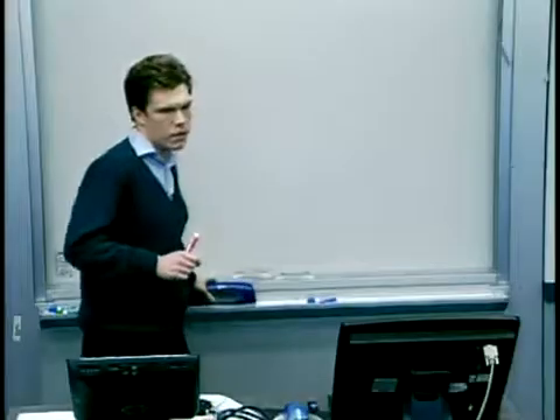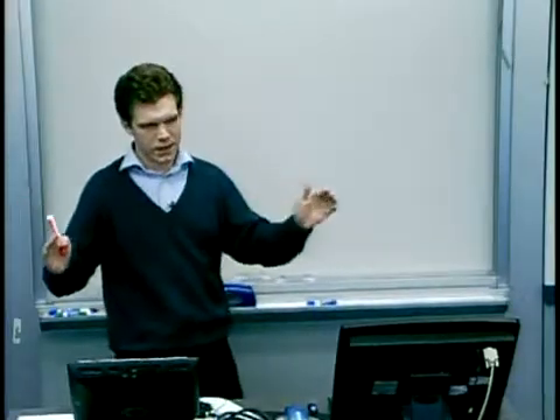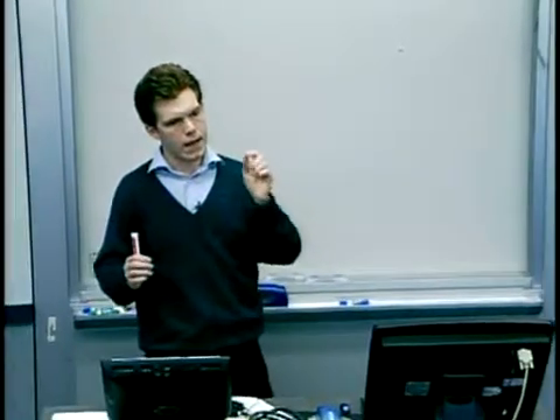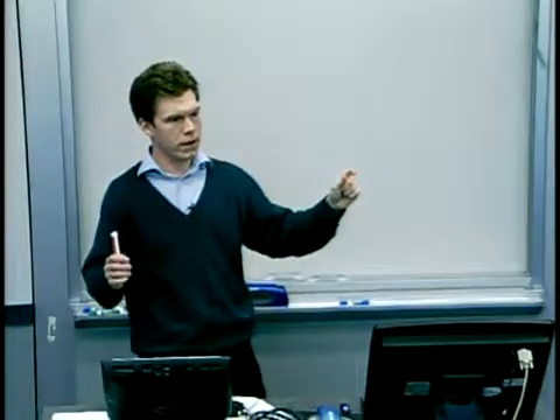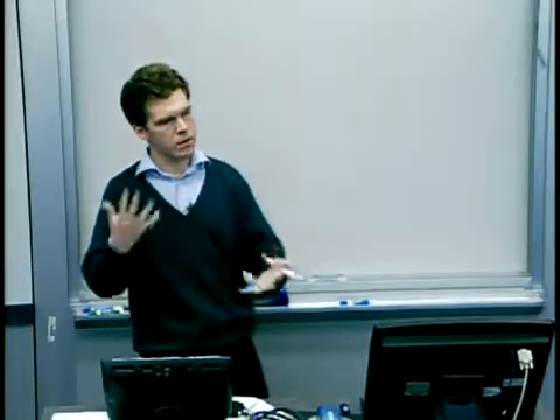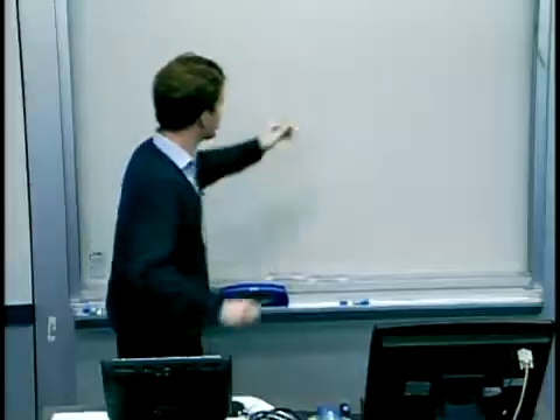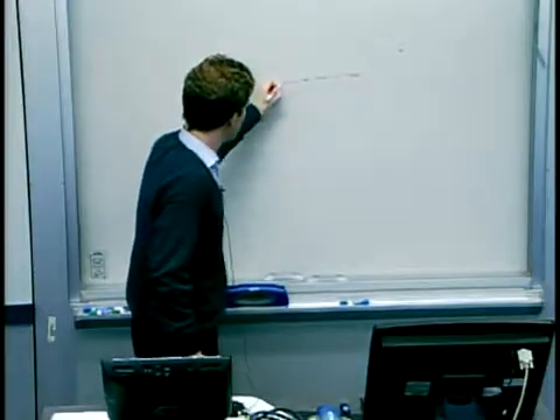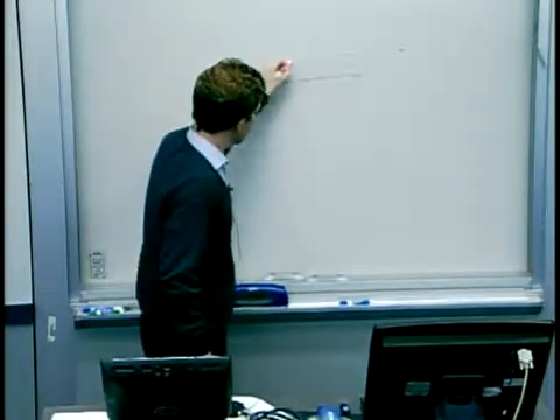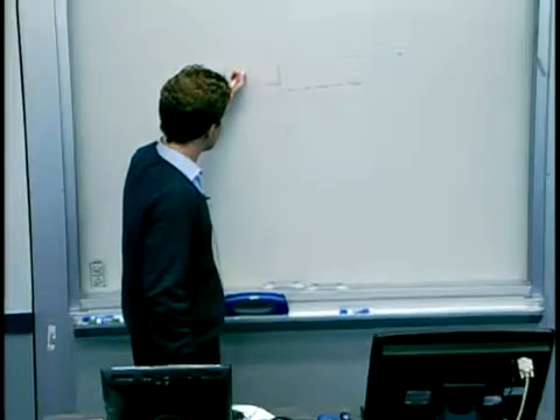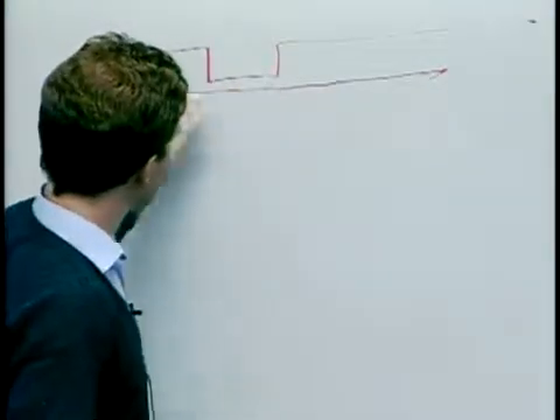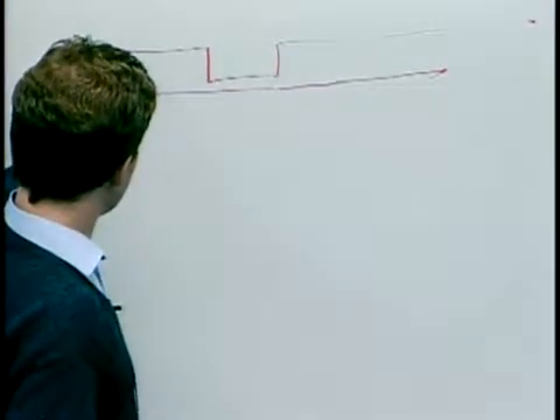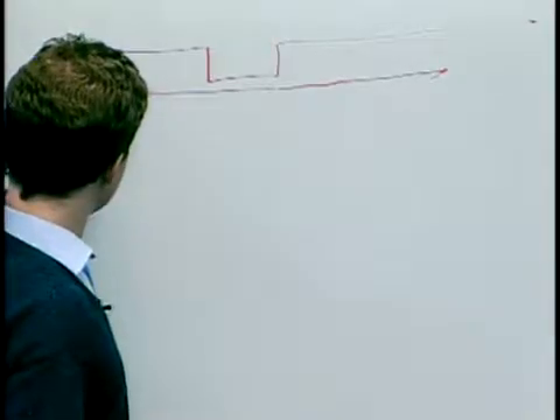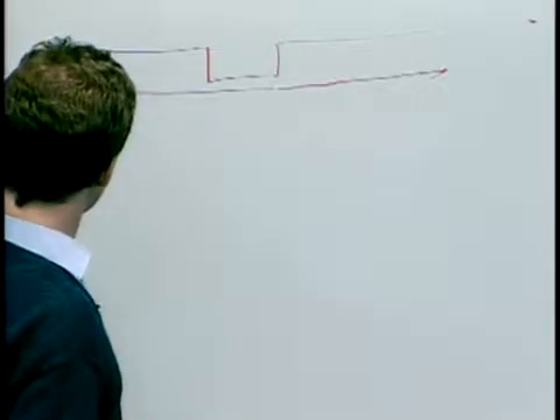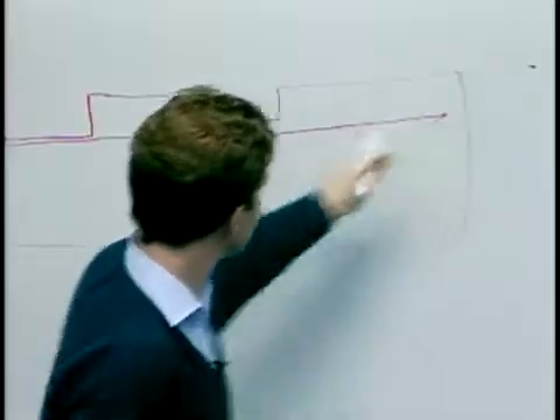And if the residual layer varies in thickness, the time taken to break through it will be different, and then you'll get different properties of the underlying structure. So let's say you've imprinted this 100 nanometer thick polymer layer, and on this side the residual layer is really thin, and on this side it's twice as thick.